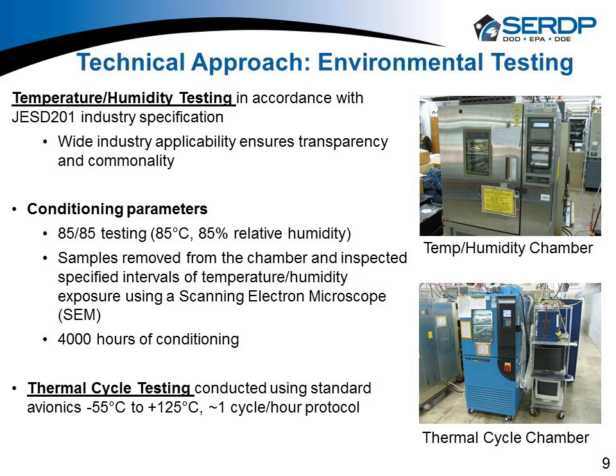The primary thing we subjected all the test samples to was high temperature, high humidity, 85 degrees C at 85% relative humidity. The industry has shown, and other NASA projects have shown, that that's a zone that really wants to promote whisker initiation and growth. And so we use that for almost all of our testing. The samples would go in and out of the chamber at specified intervals, and then were inspected using a scanning electron microscope. In industry, we use the JESD 201, so we followed that format for the most part. That does two things for us. One, it's transparent. Other people in the industry doing this type of testing could relate to this testing very well, and then they also could compare their results to the results that we would generate throughout the testing program.